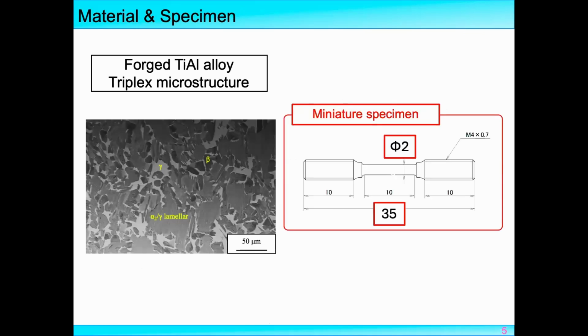The material is a near-lamellar forged titanium and aluminum alloy, which has a triplex microstructure. The microstructure is given here. Here we can see that the large grain is the lamellar phase, the white grain is the gamma phase, and the dark grain is beta phase. The miniature specimen used in this study is given here. The total length of the specimen is 35 millimeter. Its gauge length is 10 millimeter with diameter of 2 millimeters.